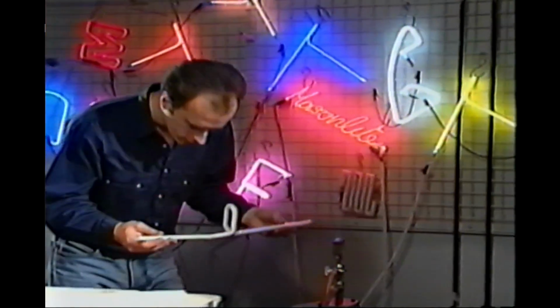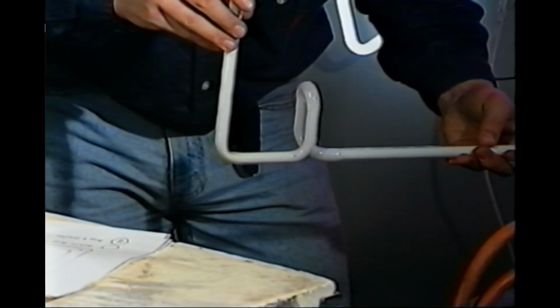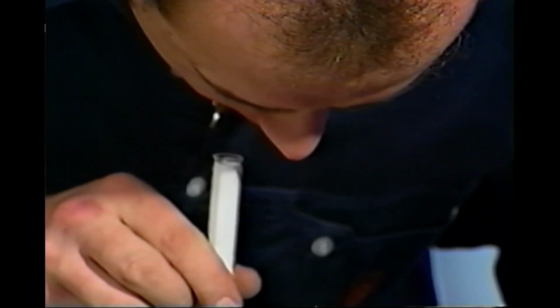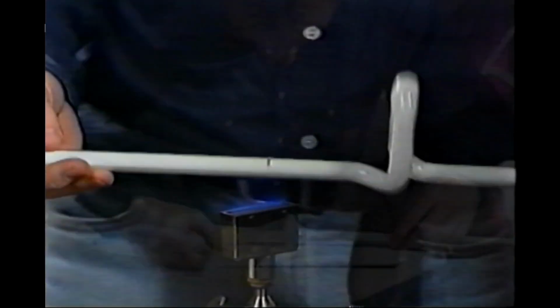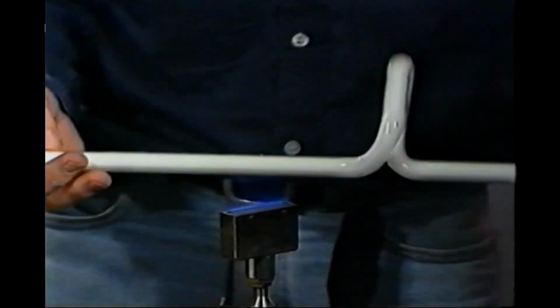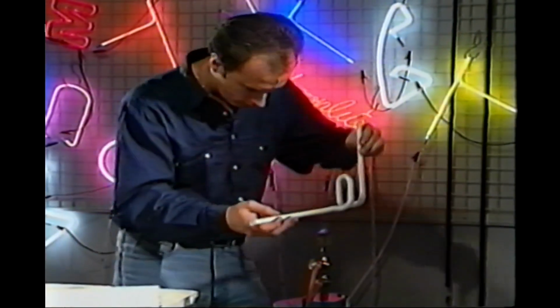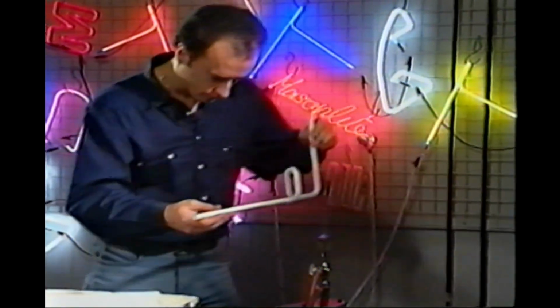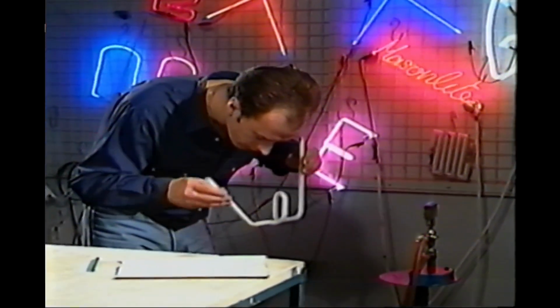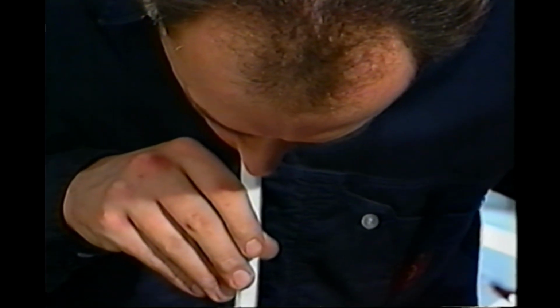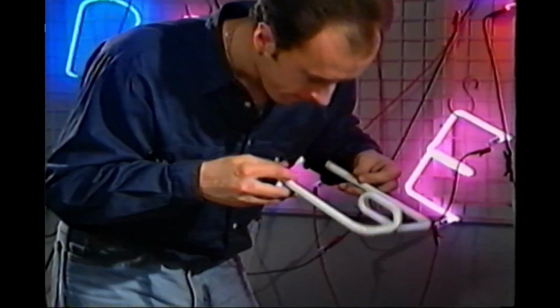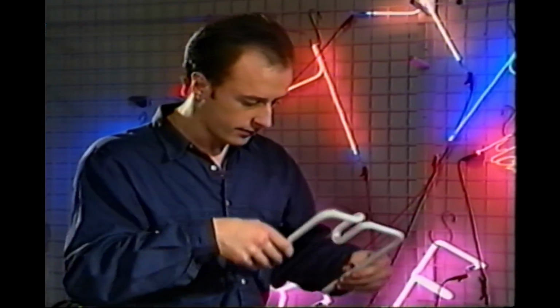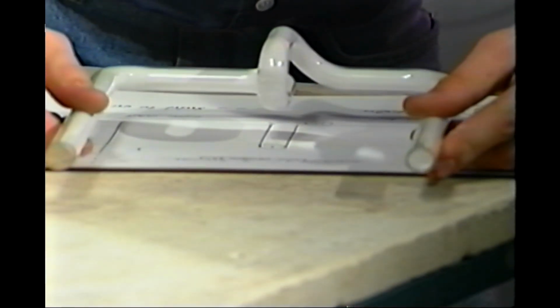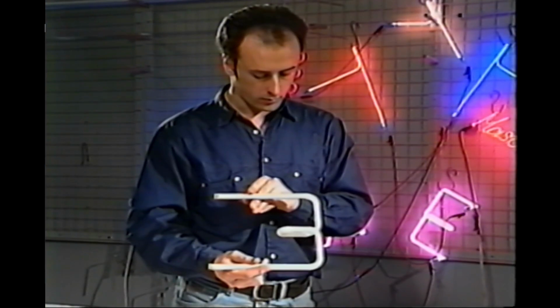Secondly, and related to the width of the melt, is the amount of heating required. Generally, the glass need only be melted sufficiently to enable the correct shape to be formed, with good tube diameter, thickness, and uniform powder coating. Overmelting can lead to phosphor damage, including stretching and thinning of the powder coating. Undermelting will result in the glass folding instead of shaping, leaving a poor quality bend, and in extreme cases of underheating, phosphor may drop off during and after the formation of the bend.